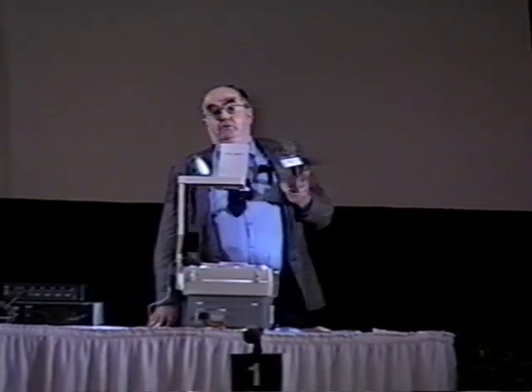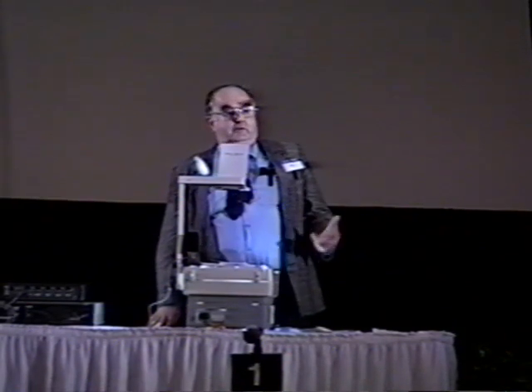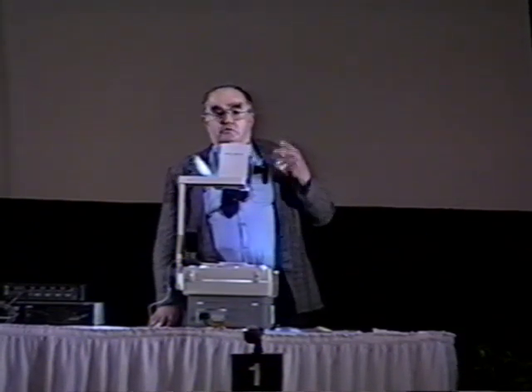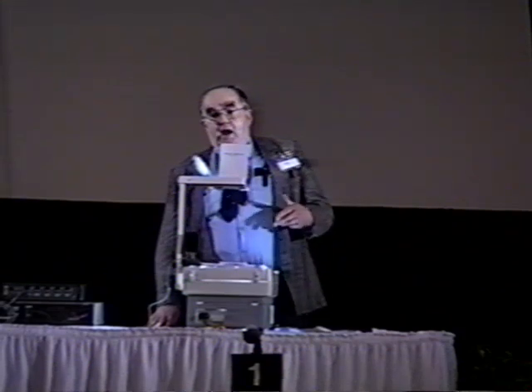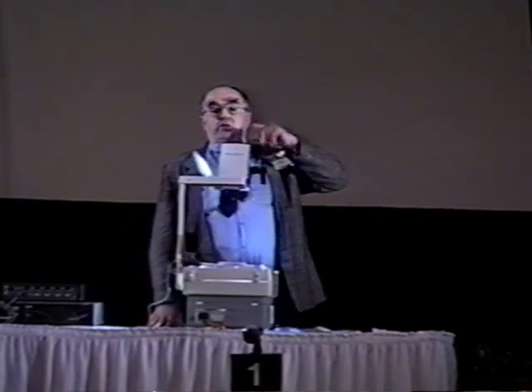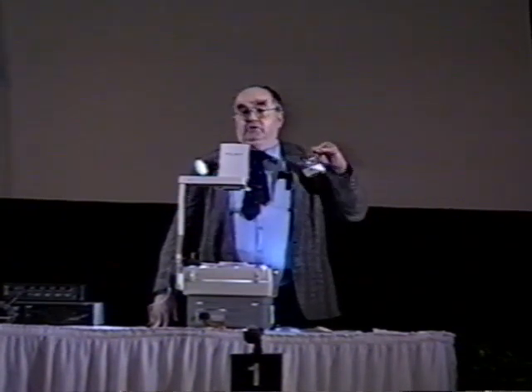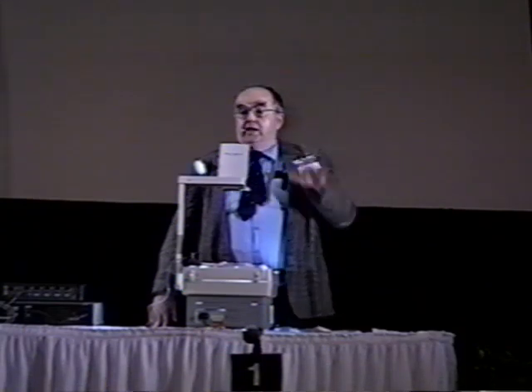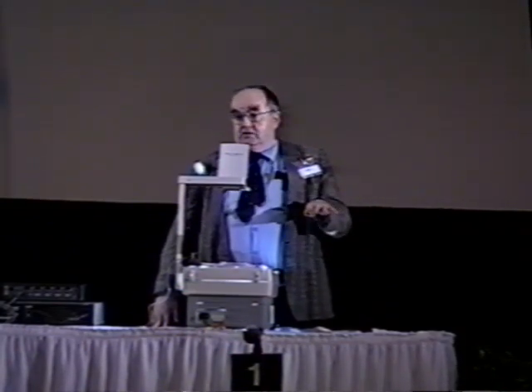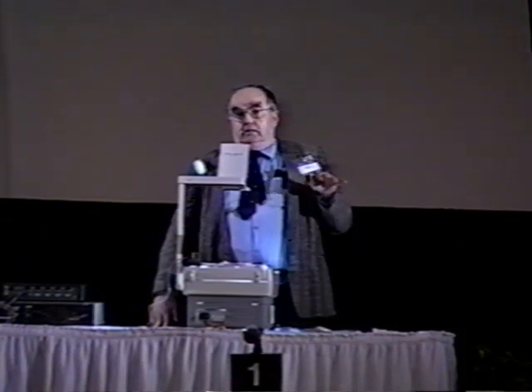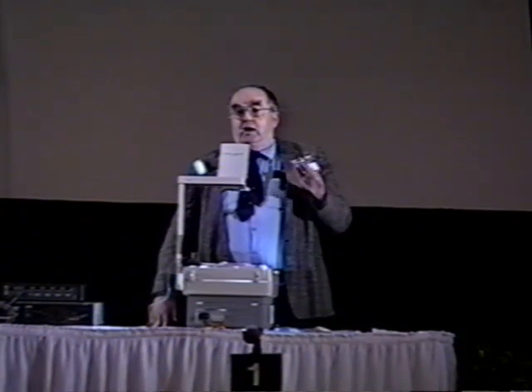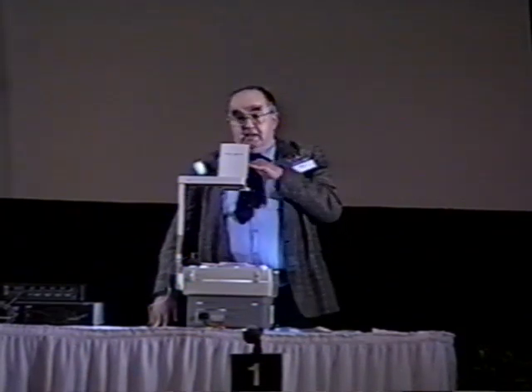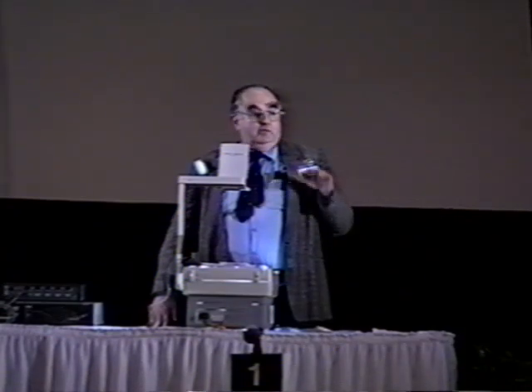And then I would vent it, and frequently I would get a little bit of steam condensation in the vent, indicating that there had been some reduction of an oxide on the catalyst. So I'd have to evacuate with a vacuum pump, put in some more hydrogen, and do this all over again. I would do this sequentially with hydrogen until the asymptotes were within a half a degree or 1 degree or so of one another. At that point, I felt comfortable that I knew what the baseline was for that particular catalyst. And I could then, on my next go-round, evacuate and load the deuterium, put in the same power, and see what temperature would result.